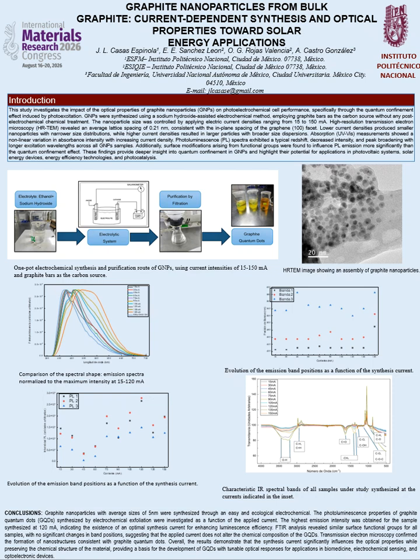400 to 700 nanometers. HRTEM image analysis showed that the resulting GNPs were well dispersed with excellent solubility, and the particle size, measured by counting 10-15 individual nanoparticles, revealed a size distribution with mean sizes of 2.44, 3.66, 3.91, and 6.80 nanometers, as determined by statistical image analysis of the 4 samples.